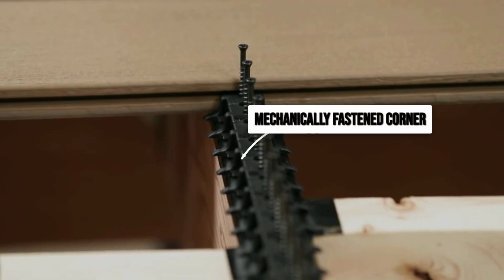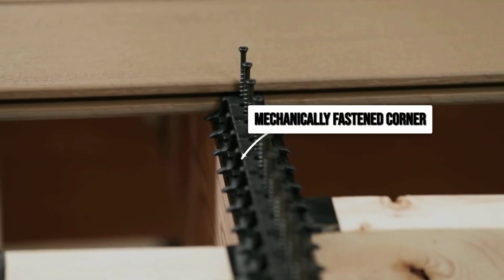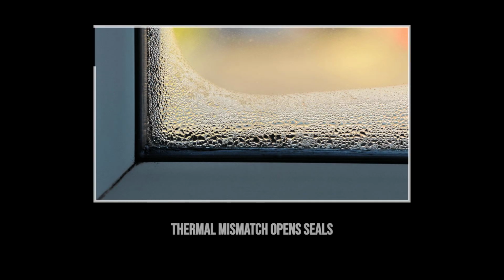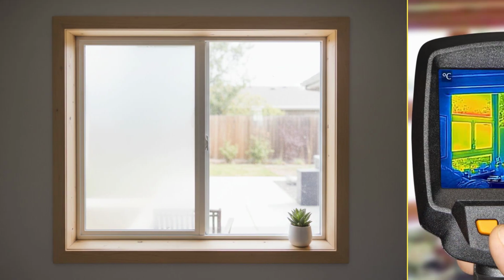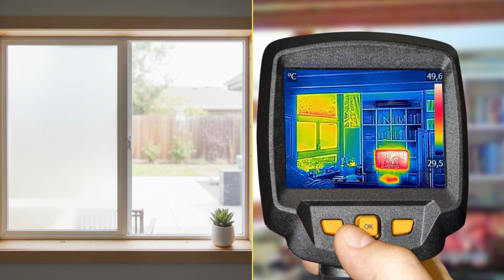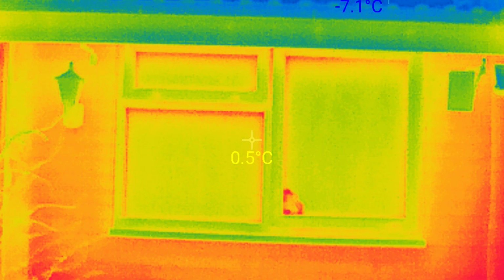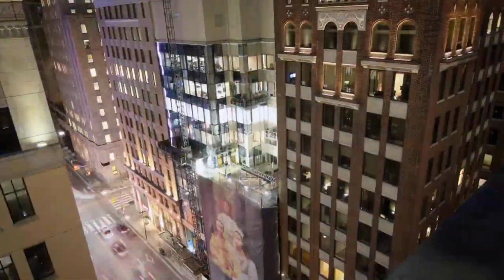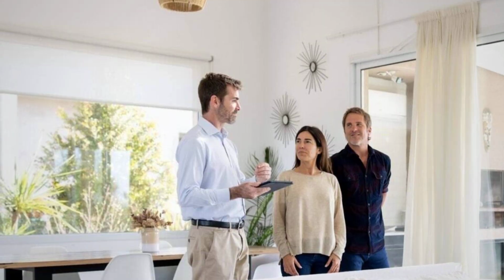In a builder-grade unit, where corners are mechanically fastened instead of fusion welded, that same movement works the joint open season after season until the seal between the two panes of glass is gone. When that seal goes, the inert gas fill, argon or krypton, escapes. Your double-pane window becomes a single-pane window with a permanent fog between the glass. The insulating performance drops immediately. The only fix is full glass unit replacement. Nobody mentions that at the walkthrough.